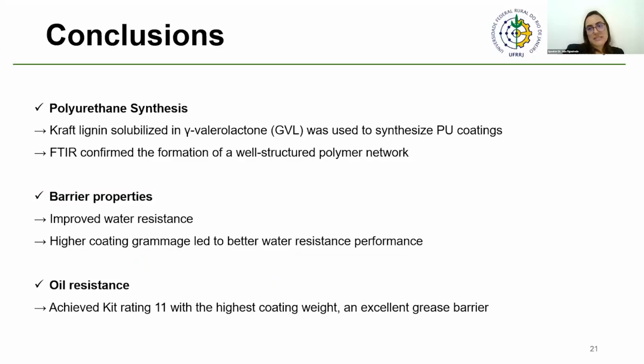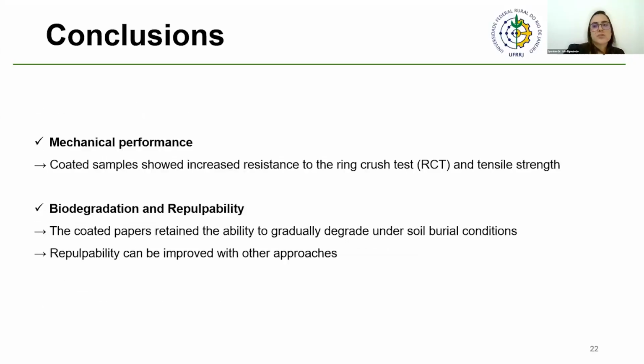So in conclusion, the polyurethane synthesis was successful. The application of these materials as a paper coating resulted in effective barrier properties without significantly compromising mechanical performance. And the choice of coating grammage should consider the most relevant end-use property. For instance, if burst resistance is essential, intermediate coating levels are recommended, as they still provide barrier properties. And while both biodegradability and repulpability show potential, further optimization and probably another approach is needed to increase the performance of this analysis.